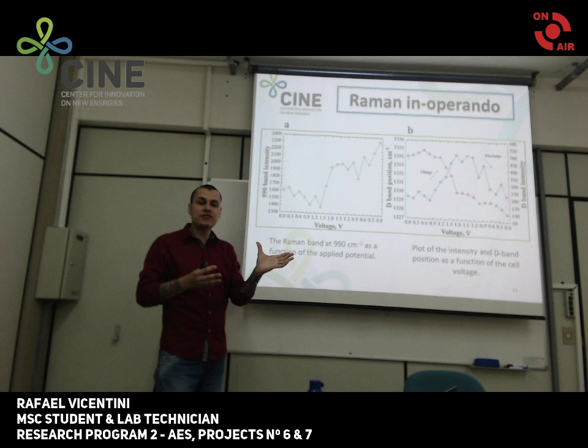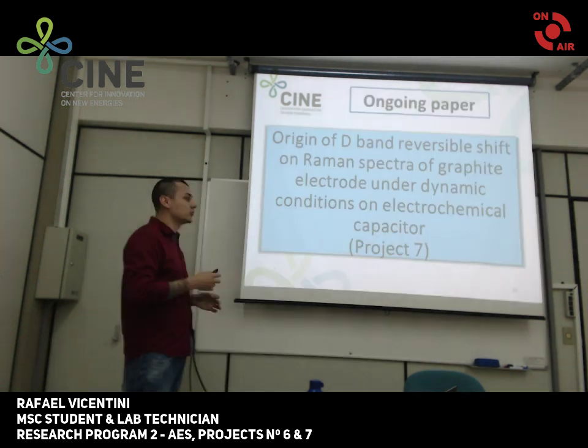After these findings, I asked myself, what does the D-band shift mean? Since then, I have been working to better understand this point, studying the fundamentals of the Raman spectrum, trying to understand why the D-band shifts under dynamic conditions. So we have been doing tests under dynamic conditions using graphite. And maybe you can ask me, why have you been using graphite? There is a simple reason: graphite has only carbon bands in the Raman spectra. Because of this, we have been writing a paper named Origin of D-band reversible shift on Raman spectra of graphite electrode under dynamic conditions on electrochemical capacitors. This paper only involves project 7.